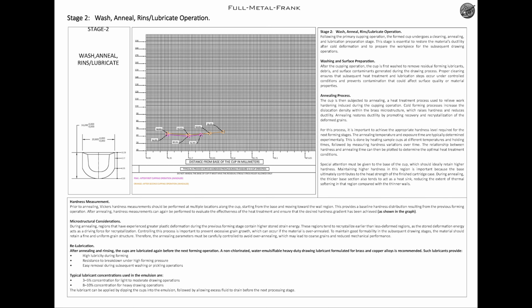Cold forming processes increase the dislocation density within the brass microstructure, which raises hardness and reduces ductility. Annealing restores ductility by promoting recovery and recrystallization of the deformed grains. For this process, it is important to achieve the appropriate hardness level required for the next forming stages.